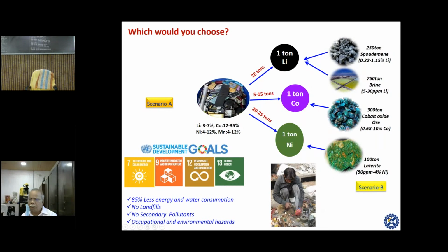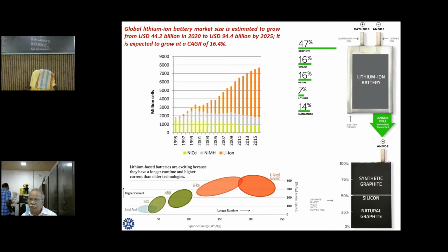And of course, there are no occupational and environmental hazards, because you process the entire battery and get the powder and go ahead with it. I break the battery into several parts. The main part is the aluminum foil, which contains the cathode, and the anode part is the one which contains graphite and some amount of silicon. The lithium ion battery, if you see a breakup, contains 47% carbon material, followed by the highest amounts of cobalt and nickel, the costliest ones, followed by lithium and manganese. It depends upon the manufacturer whether they want to increase the content of these metals to suffice the cost of production as well as availability of metals.